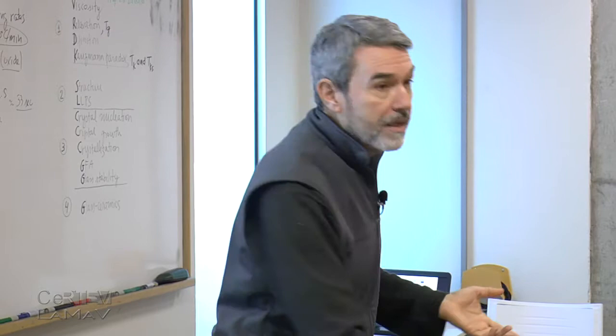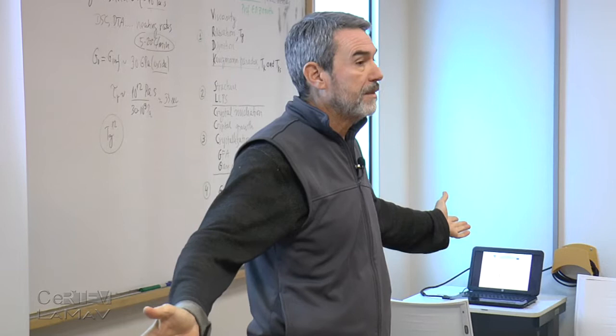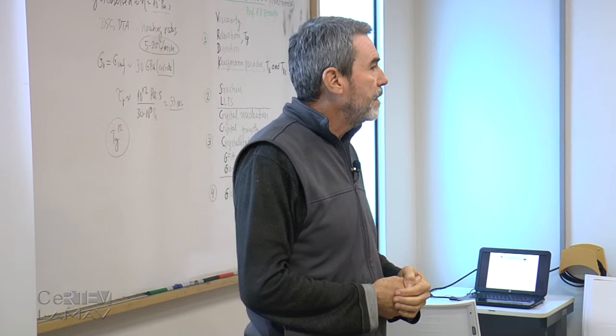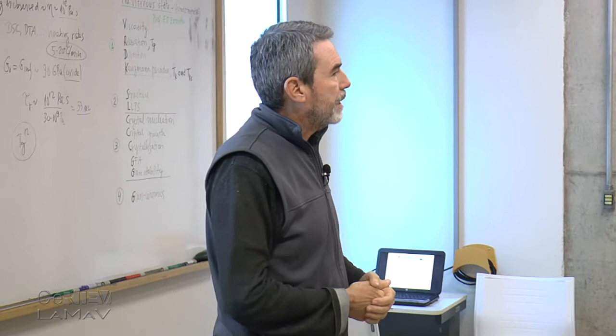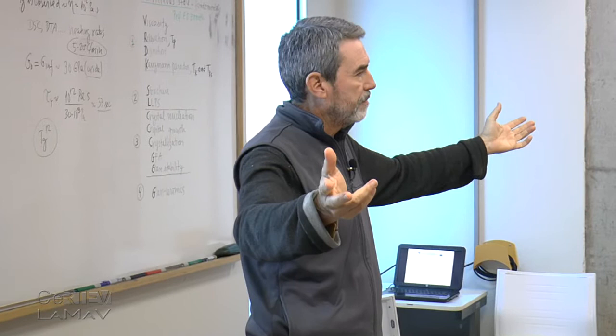How many of you have seen a glass breaking? I have seen one spontaneously break, maybe two or three times in my life, in my house or so. Boom, a glass has shattered. Why? Because it has internal stresses which cause some cracks to slowly grow, and sometimes they break. You know, there's slow crack growth and other problems. So annealing is a very important operation.